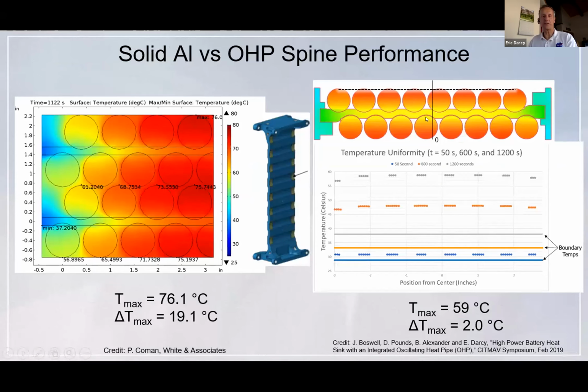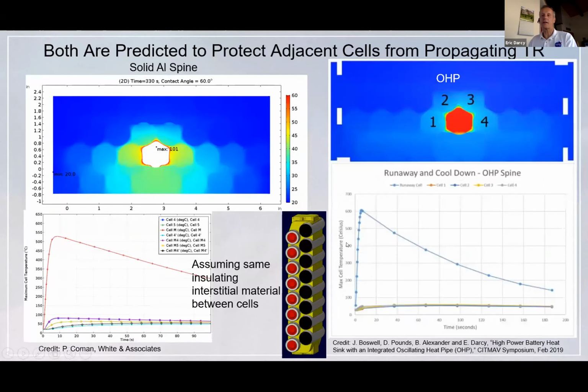Here you have a side-by-side analysis comparison. If you went to a solid aluminum spine, we'd have temperature gradients between the hottest and the coldest cell of 19 degrees. While the oscillating heat pipe, with the ammonia bubbling and condensing that occurs from the middle to the ends, greatly reduces that thermal gradient from the hottest to the coldest cell to 2 degrees Celsius. That's what the modeling predicts. The modeling also predicts that they are equally good for protecting against a single cell thermal runaway.